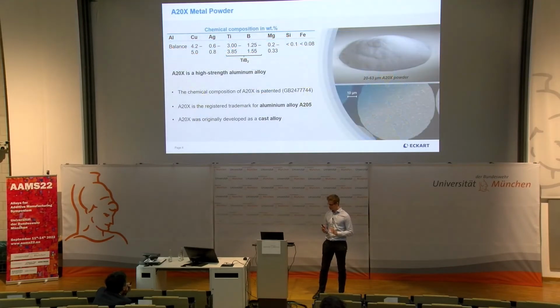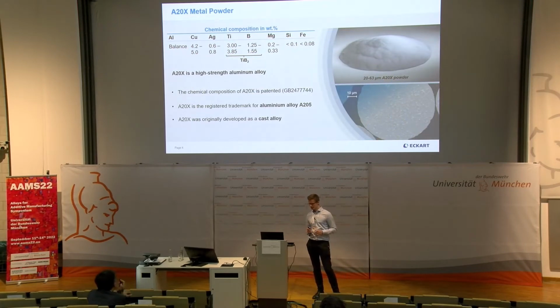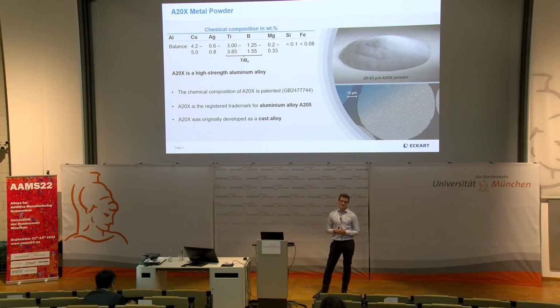So the chemical composition of A20X is shown in this table. It's essentially an aluminium, copper, magnesium, silver alloy with additions of titanium and boron, which are present as titanium diboride ceramic particles. So A20X is patented and was in the past supplied by a company called Aluminium Materials Technology, AMT, in the UK. This company was acquired by Eckart, including the patent, so now this product is supplied by Eckart.